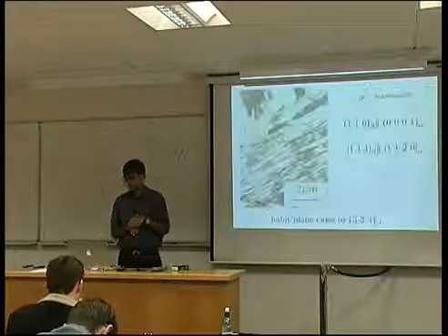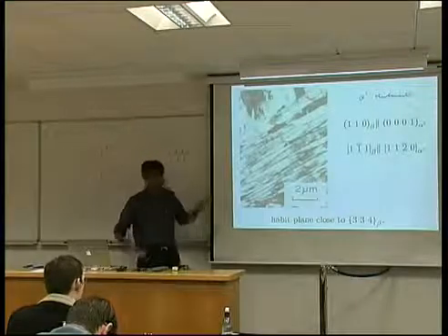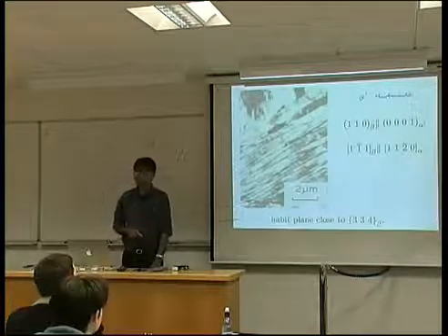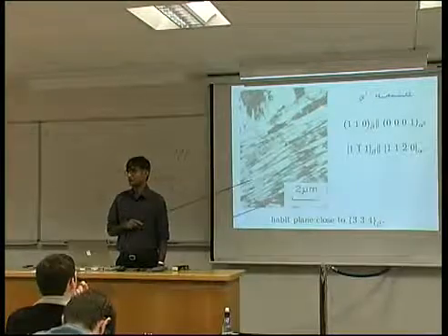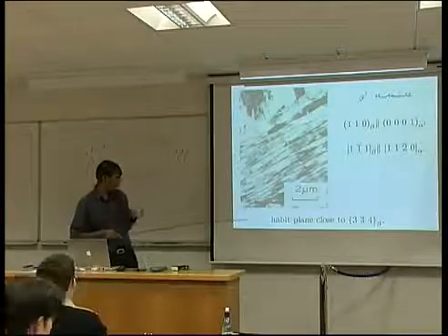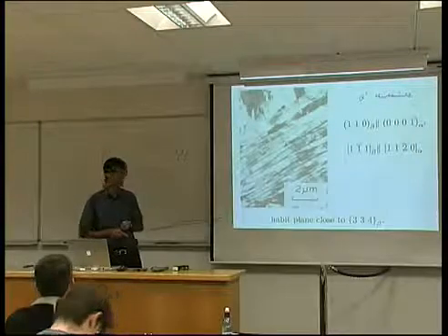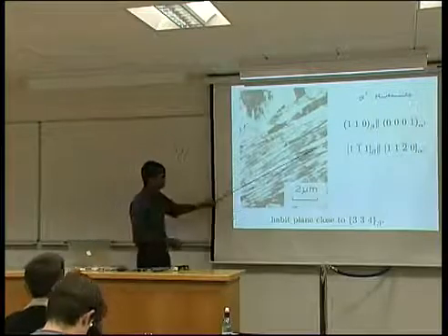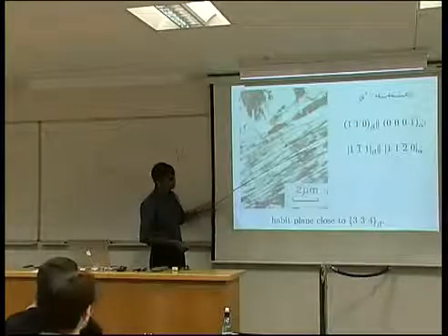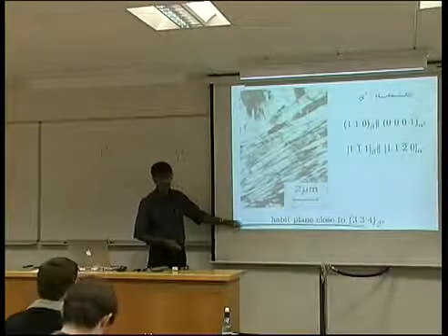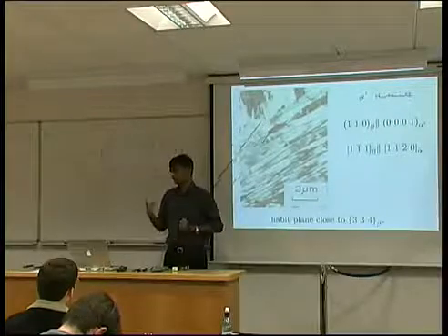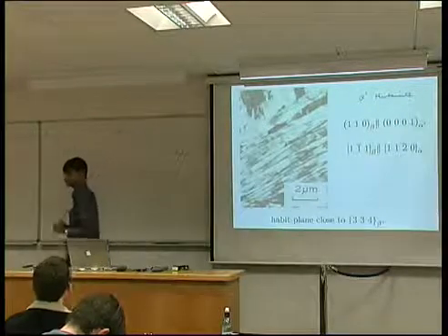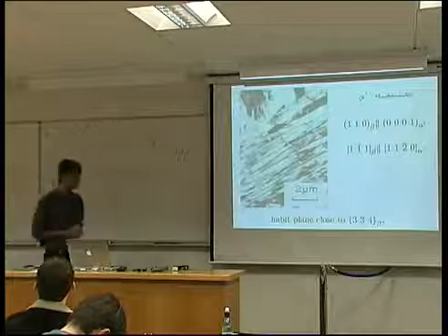Okay, let me just show you first of all the microstructure of martensite in the form of thin plates, and we'll understand why martensite forms as thin plates in the next set of lectures, where we'll look at the mechanisms of martensitic transformations in general. And the plane on which the martensite forms is known as the habit plane, and this just happens to be a strange plane which is close to 334 beta. At the moment we don't understand why, but you will after the next two lectures.